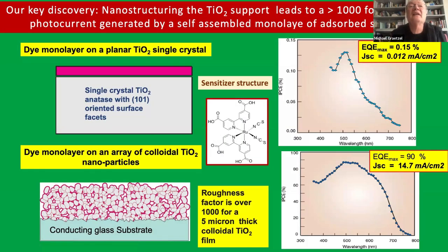And so at the end, I mean, when we compare the planar surface that Professor Goodenough, who later won a Nobel Prize for his battery work, used, the same surface facet with a single crystal, and this disordered array of nanoparticles, we found that we could increase the photocurrents over 1,000 times. That was the breakthrough discovery. And you can see here the IPCE, that's the external quantum efficiency. So 80 or 90 means out of 100 incoming photons that strike the cell, 90 will be making electrons. Okay?